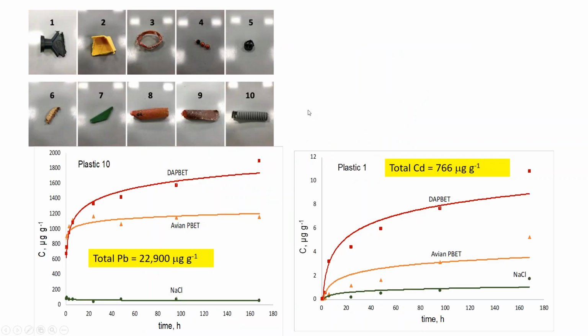And here's some results hot off the press. These were generated a few weeks ago, actually. What we have here is we subjected 10 plastics to an avian, if you like, digestion, acid in seawater, and also what's called a dietary adapted PBET. So this is the digestive system, sodium chloride, this is it with acid, and this is it with acid and the fish oil. And you can see that with the fish oil, we get significantly more of these additives coming out compared with the acid.